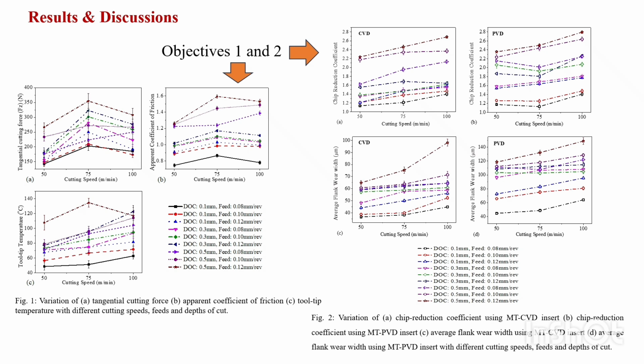The apparent coefficient plot maintained similar patterns. The tooltip temperature had maintained an increasing trend with increasing cutting velocity and feeds. The highest tooltip temperature we can see at the intermediate level of cutting velocity, due to low thermal conductivity of the alloy and increase in cutting velocity, which provided lesser time for heat dissipation.